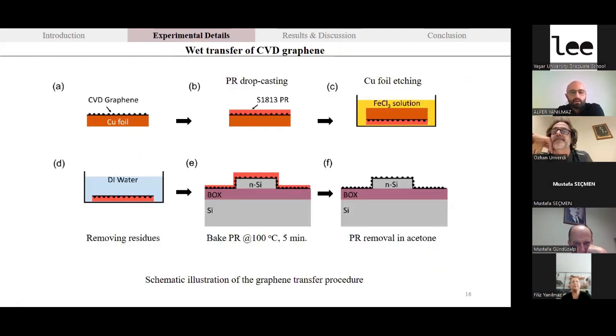Graphene transfer requires 6 different steps. Here is the copper foil with the grown graphene on it. After drop casting of the photoresist onto the graphene side, we etch the copper foil using ferric chloride solution. After removing the ferric chloride residues with DI water, we bake the photoresist-graphene onto the desired substrate at 100 degrees Celsius for 5 minutes, and then we remove the photoresist using acetone.